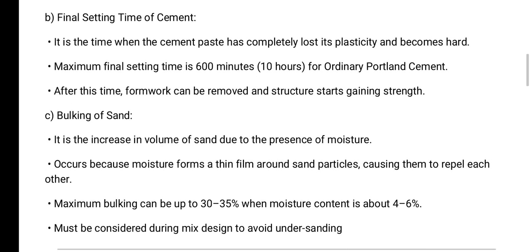Bulking of sand. It is the increase in volume of sand due to the presence of moisture. It occurs because moisture forms a thin film around sand particles, causing them to repel each other. Maximum bulking can be up to 30 to 35% when moisture content is about 4 to 6%. Must be considered during mix design to avoid undersanding.